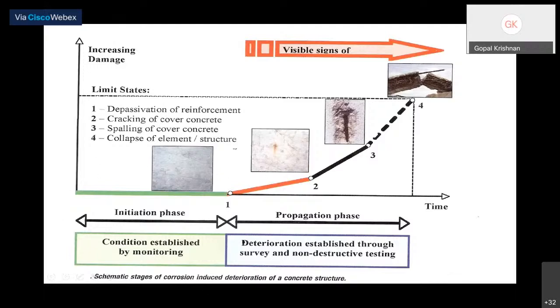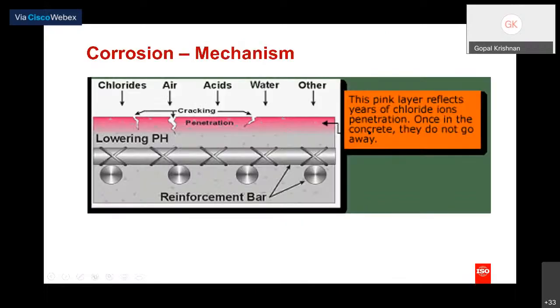So one is the initial phase, second the propagation phase. In the initial phase, the condition is established by monitoring. We can only observe, we cannot do anything more. But in the propagation phase, deterioration is established through survey and using non-destructive testing techniques. So I think this is clearer for understanding the 4 stages of corrosion activity. You all know the corrosion mechanism. If chloride, air, acids, water, or other chemical or hazardous substances enter the reinforcement, corrosion starts. Instead of talking, let me explain through one of the audio visuals.